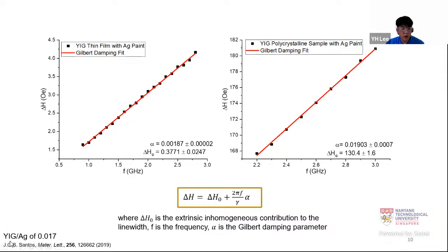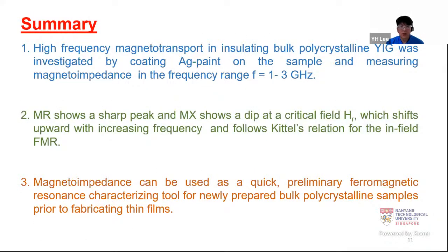we compared with one of the available literature values from J.C.B. Santos. His YIG capped with silver metal, the Gilbert damping parameter is about 0.017, which is quite close to our 0.019. Hence, in this case, we would like to conclude that in our investigation, the high-frequency magnetotransport